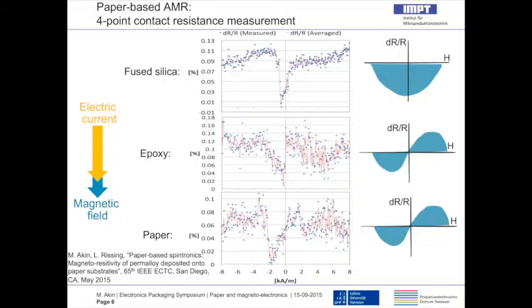For the reference sample, the fused silica substrate, we measured what we are supposed to measure, an increase in electrical resistance, comparing that with the characteristics I showed you in the previous slide. On the paper and the epoxy samples, we see something similar to the plus minus 45-degree response. The method we use to obtain these characteristics is the 4-point contact resistance measurement, which is usually not meant for soft materials. This is something that you push on a substrate. You indent into the coating, and if the bottom substrate is soft, it will not withstand the spring pressure applied by the probe needles, and you might get some side effects. So after doing some processing, we obtained these characteristics.